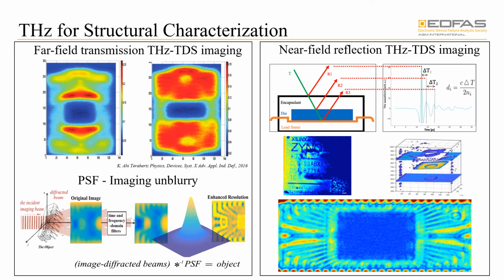The internal structure is able to detect features such as bond wires. However, it should be noted that the main drawback of the near-field detection is that it has a very slow acquisition time. From our experience using the system in our lab, it takes 10 or even more hours to raster scan a sample and generate a high resolution image. Also, since it's in reflection mode, it is able to characterize the 3D volumetric information of the sample. Based on the equation shown here, we see that knowing the refractive index and the time delay, the thickness of different layers can be calculated.